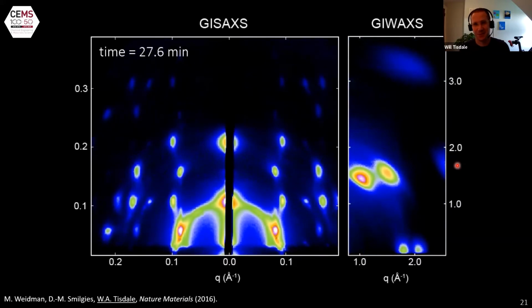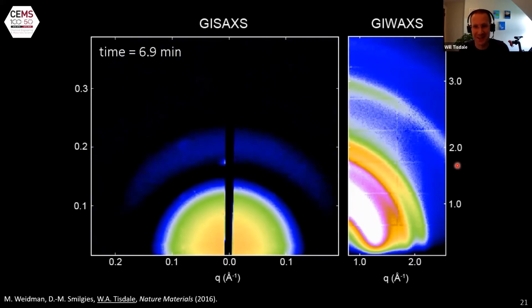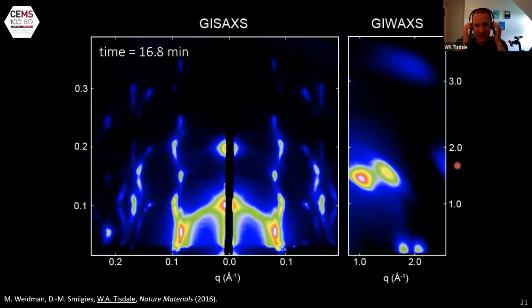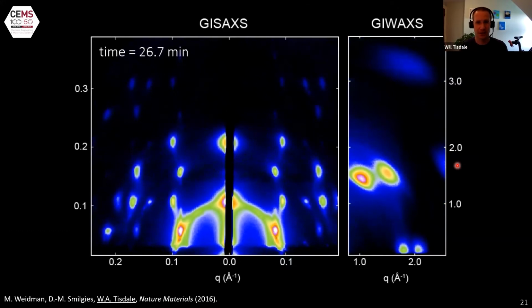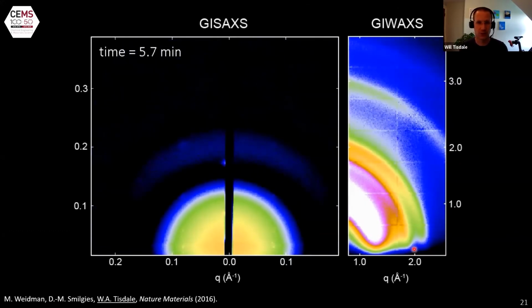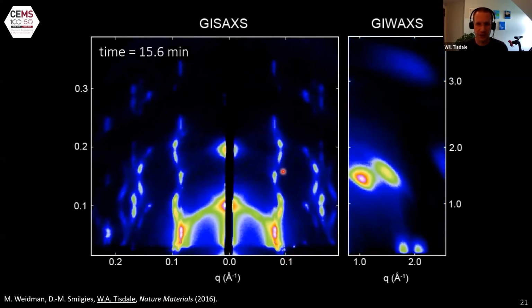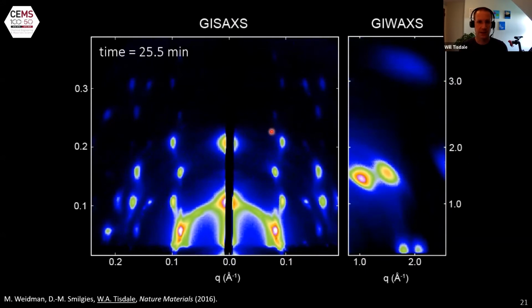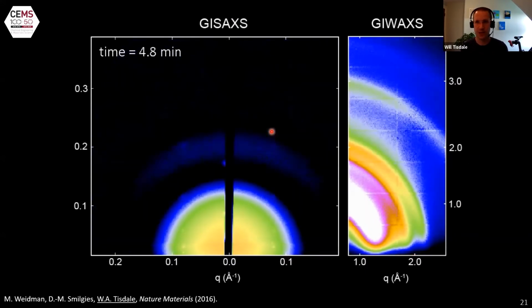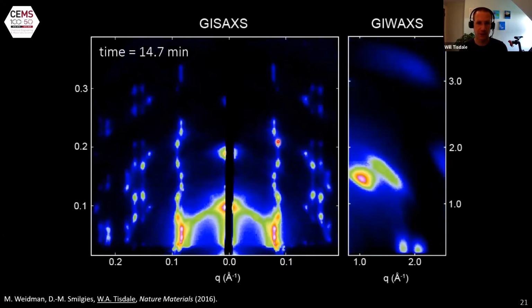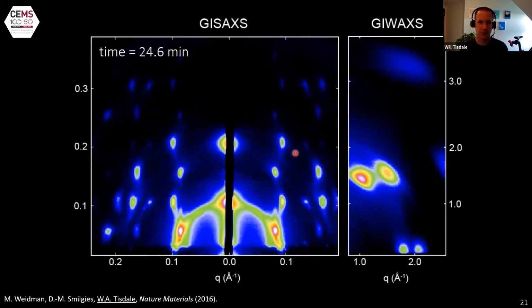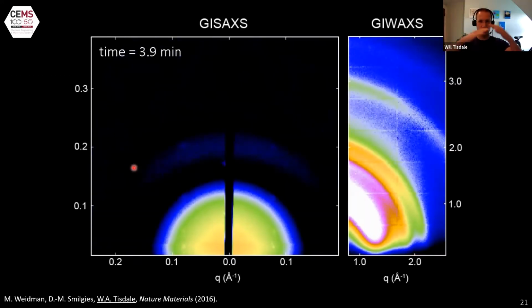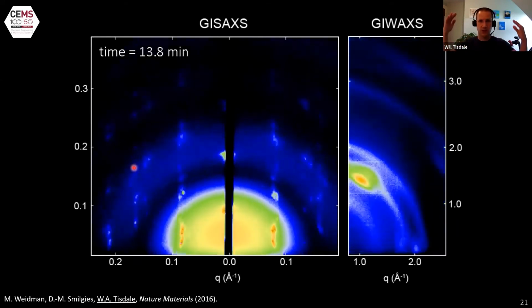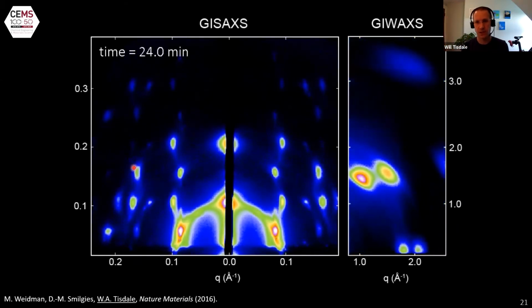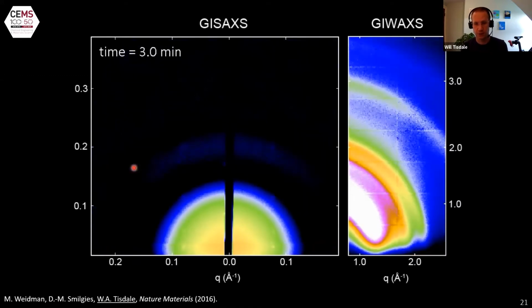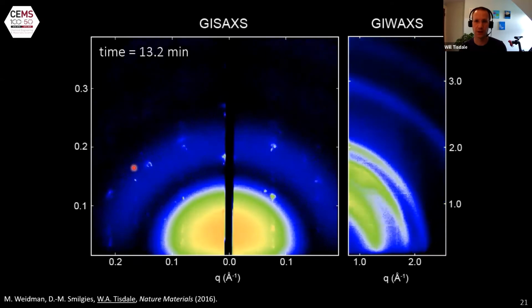Ooh, that was the first thing I said when I saw this data when Mark brought it home. I thought this was just about the coolest thing I'd ever seen. You're watching a phase transition happen from a disordered colloid to an ordered superstructure. What's particularly interesting is that the initially formed superlattice is not the final superlattice you wind up with. The superlattice structure evolves and changes over time. You can watch these peaks merging into each other. You see at later times, the whole scattering pattern moves outward. That expansion makes sense. An expansion in reciprocal space is the same thing as a contraction in real space. And we assume that that's just associated with drying, removal of residual solvent. But there's something else more complicated going on.